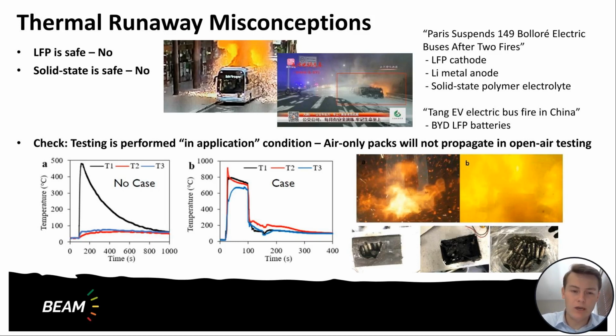The other misconception I want to cover is that when looking at battery pack solutions or claims of preventing thermal runaway, you just really want to make sure that this is an in-use application analysis. And why is that? Well, it's actually a much easier requirement to pass thermal runaway propagation testing, so to prevent the propagation from a single cell failure, in open environments. So if you look at testing that we've done internally to prove this out, we took